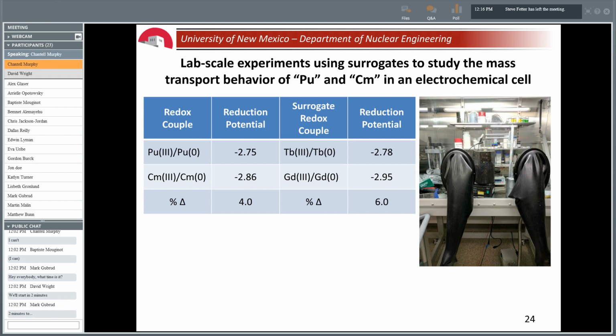Unfortunately, plutonium and curium are not readily available for experimental use, so I use surrogates. The electrochemical parameters of interest were the valence state of the ion undergoing reaction and the reduction potential difference of the two elements. Literature review led me to terbium and gadolinium. The valence states of the reactions match, and the reduction potential differences are pretty close. The percent difference of 6 versus 4 is okay. I think I can make the argument that because the percent difference is larger in my experiment setup, if co-deposition occurs, if gadolinium does end up following terbium, it's easier to make the case that co-deposition could occur with plutonium and curium, because their potentials are even closer.